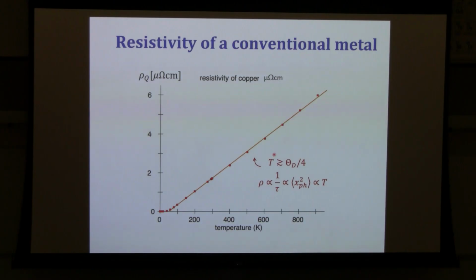And then below a certain temperature, the phonons freeze. The phonons become quantum. And there we have a crossover to a different regime where the resistivity is typically T to the 5th power from electron-phonon coupling, acoustic phonons. The prediction is that it should go like T squared ultimately at very low temperature from electron-electron scattering. Okay, and all these different regimes are very well understood, and we just need to fit a few parameters from experiment and really get all this behavior.